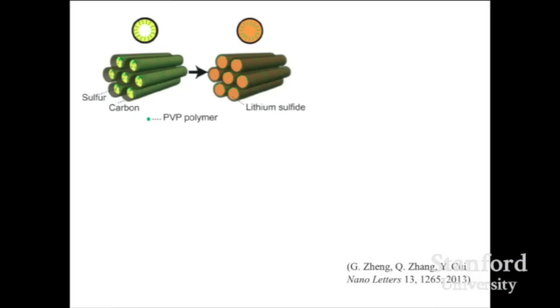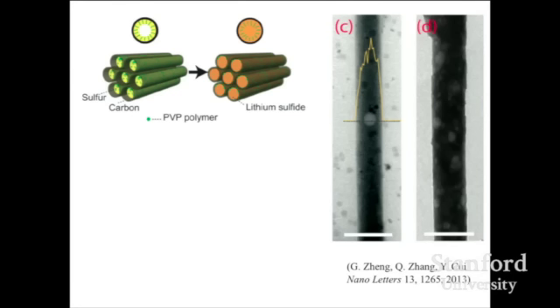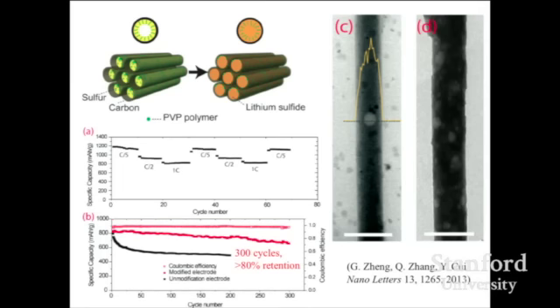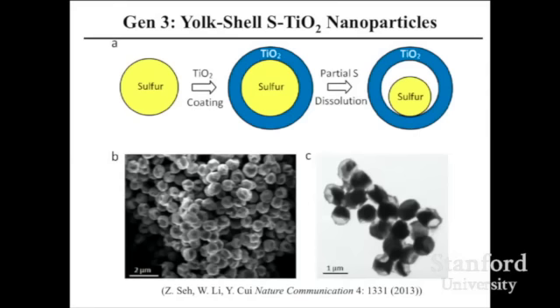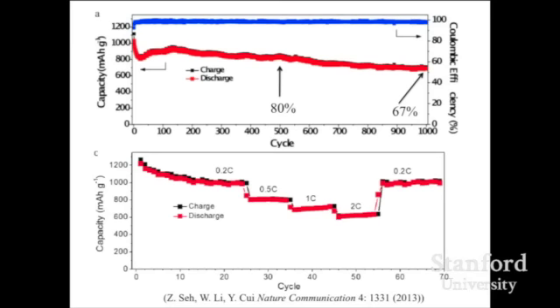Now we put PVP polymer inside and then coated sulfur inside. After you cycle this, before and after, you don't see those bead phenomena anymore. The battery cycles right here, 300 cycles, quite stable. So we finally thought we got it, using this understanding. And more cool ideas came in, similar to silicon. Pretty much we figured out silicon. We also wanted to use the same strategy for sulfur. If you can make this yolk-shell structure using titanium oxide coating, polysulfide cannot leak out anymore. Volume can expand without cracking the coating. This is a beautiful sulfur-TiO2 yolk-shell structure. This runs even longer, 1,000 cycles, with close to 70% capacity retention.